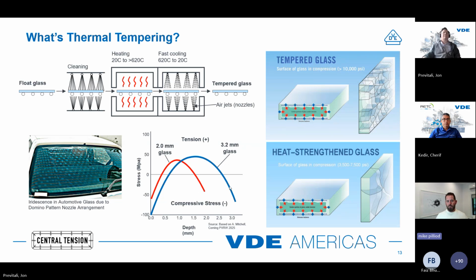And the way to think about it, when I talked about compression and then tension, is that if you took a cross section of the glass, you'll go from compressive stress on the surface down about 20%, and it'll go through a zero stress in the glass, and then it'll go into tension. And then it'll go back to compression as you go through the cross section of the glass.